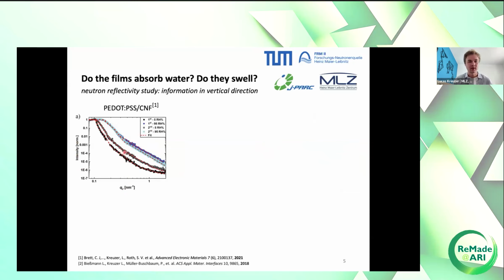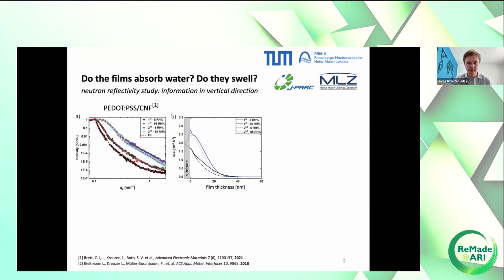So we have four of them, two black ones, two blue ones. The black ones correspond to the films in low humidity and the blue ones in high humidity conditions. So we have two cycles of exposing them to low and to high humidity. And the red dashed lines is the fit, where we apply this layer model. Now we extract an SLD profile, SLD as a function of the film thickness, SLD being scattering length density.